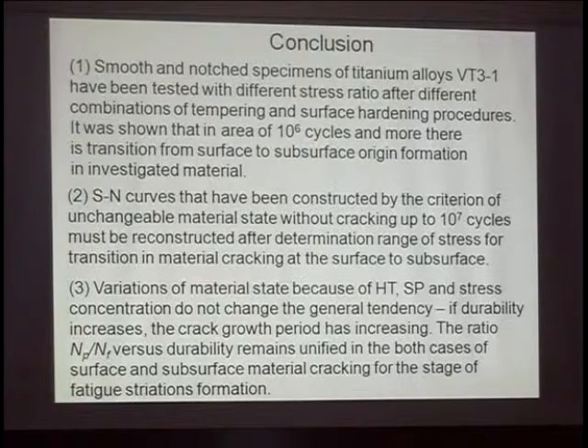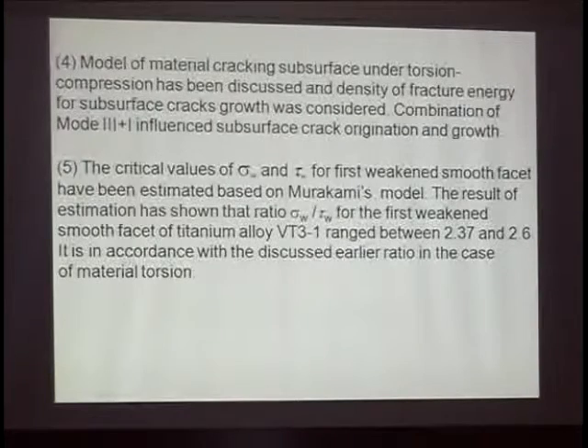It is clear that there exists a unified description between this ratio and the durability of the material, independent of the material state and the surface, whether the specimen is smooth or not. And also there exists a very clear ratio that can be used for estimating crack origination using the area for material subsurface, but it should be clear, as I just said, that there is not only one origin, there are several origins. This idea should be introduced for estimation of the stress value and the combination between shearing, twisting, and tension of material subsurface for crack origination. Thank you very much.